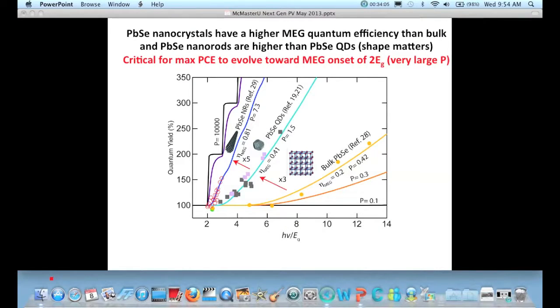And size matters. So it turns out if you just have single crystals or three-dimensional crystals, nanocrystals, you're in this region. But if you go to elongated nanorods, you improve the efficiency plot versus photon energy sufficiently so that you begin to get the staircase.